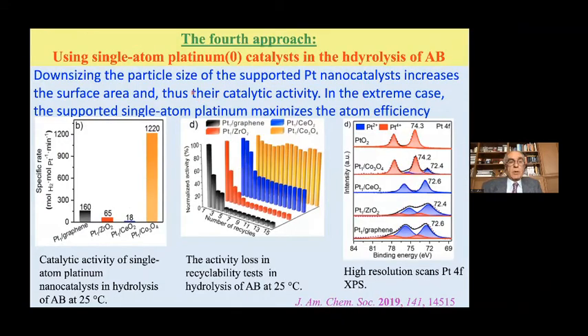Another approach is the single atom platinum catalyst in the hydrolysis of ammonia borane. In the extreme case, the supported single atom platinum maximizes the atom efficiency because we have just single platinum atoms supported on a surface. That should be highly active, and it actually is. It is a result of a study. Single atom platinum catalysts, I should say, have been generated on graphene, zirconia, ceria, and cobalt oxide. As you can see, cobalt oxide is superior in terms of activity. Also, in terms of reusability or recyclability, in that case, it is also very outstanding, I should say.